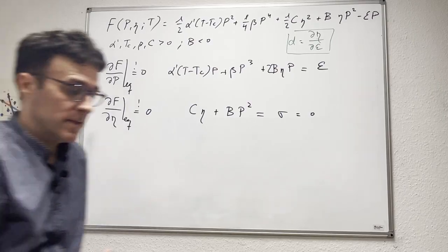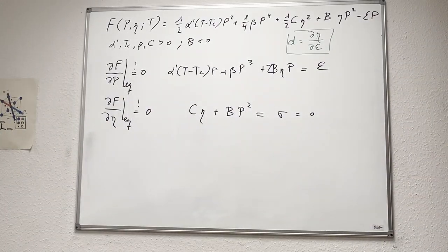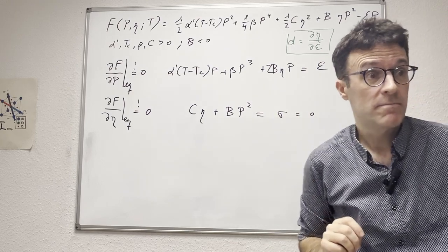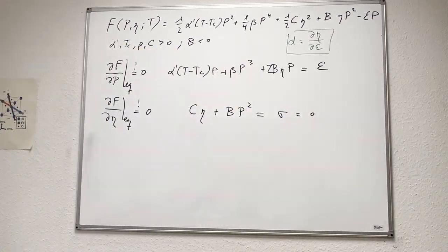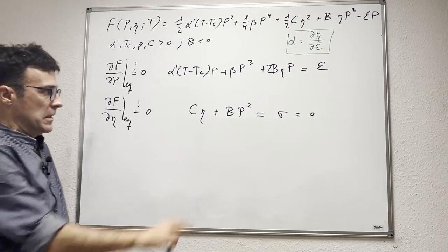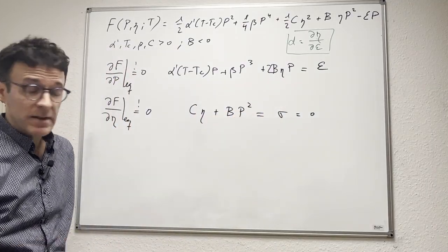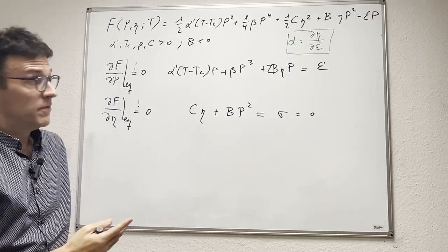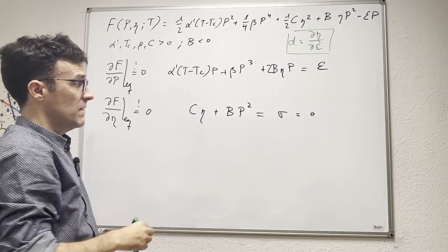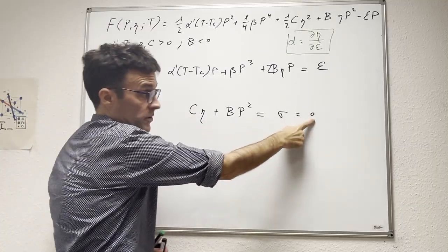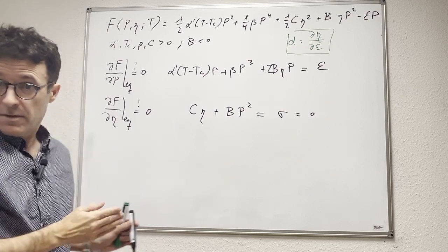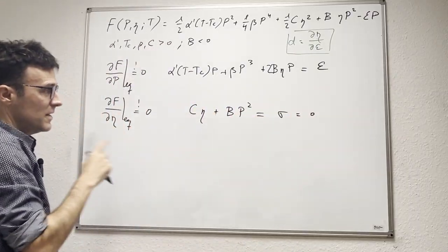So now only with that, you already see that nothing can be exactly as before, because if the strain is different from zero at the minimum, then this equation, the energetics of the polarization, will be modified. So nothing can be as before. Nevertheless, we can try to proceed almost as we did before, right? Because the part of the strain is so simple, which ultimately has to do with the fact that the strain by itself cannot do anything, as we emphasized the other day, if the polarization is zero, the strain lives in the minimum of a potential. And indeed, if the polarization is zero, that would be telling us that C times eta equals zero, which means that eta is zero. So the only reason why the strain is different from zero is that we have a polarization in this very simple theory, right? So that, in fact, this equation gives us